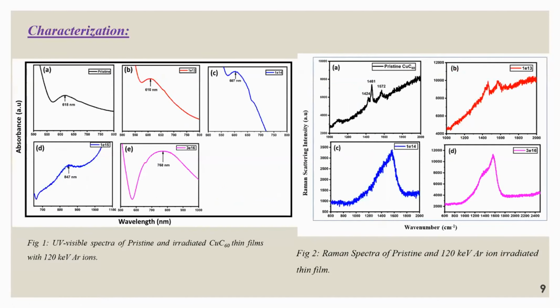These are the characterizations which we have performed. This is the UV spectra of pristine and irradiated CuC60 thin films. We have observed a sharp SPR peak at 610 nanometers, which was further red shifted to 847 nanometers and again blue shifted to 768 nanometers. These red and blue shifts are due to two phenomena. Number one, when the size of the copper nanoparticles increases, the SPR red shifts. And when the refractive index of the material changes, the blue shift is observed.